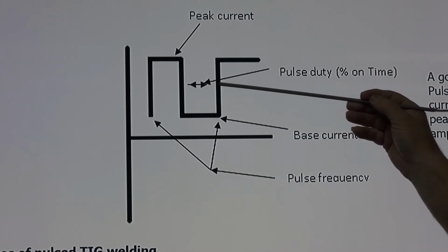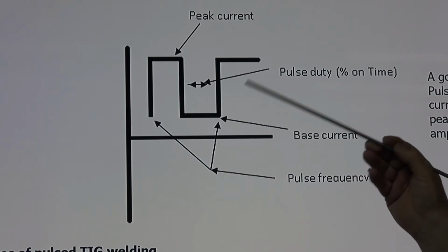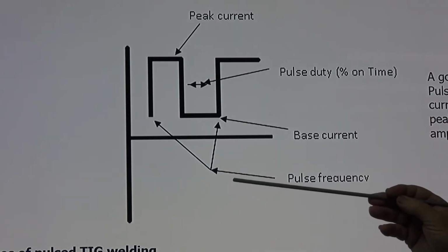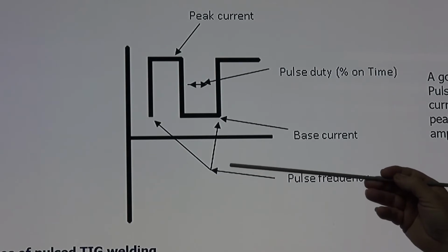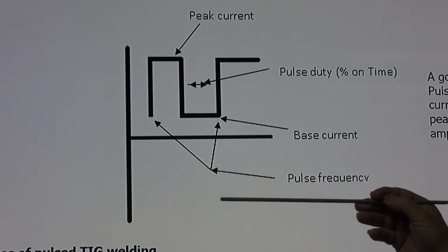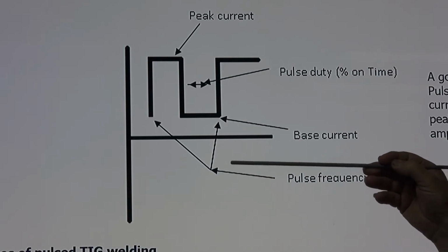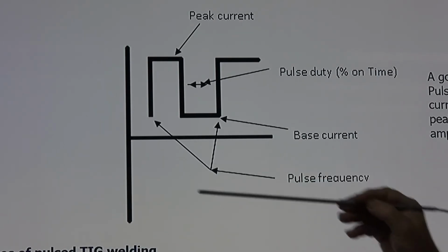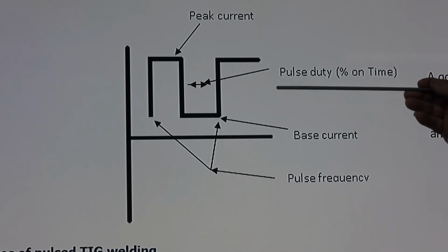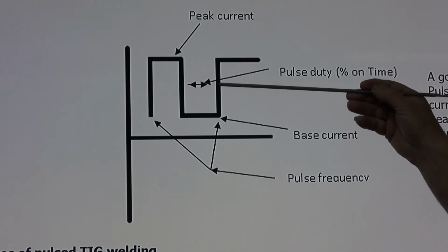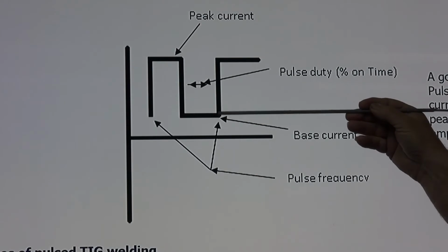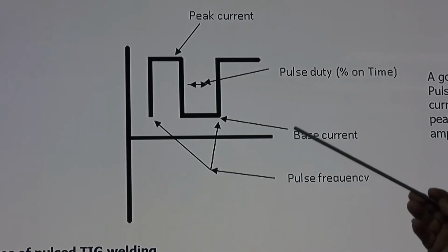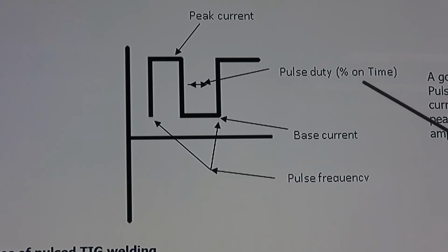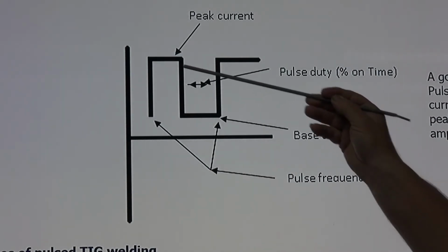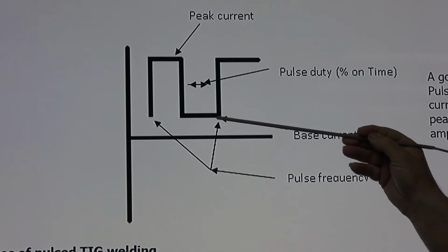The next one here is how long the pulse stays on for. You can have a fast pulse or a slow pulse. I particularly like pulses around 2.5 to 3.5 seconds, but that is personal. We can set that on the dial on the front of the machine as well. So overall, we have the pulse frequency. Now, the pulse width is the difference between how long the base current stays on compared to the peak current. A good starting point for pulse width, or pulse duty, is 50-50: 50% of the time at the peak current, 50% of the time at the base current.